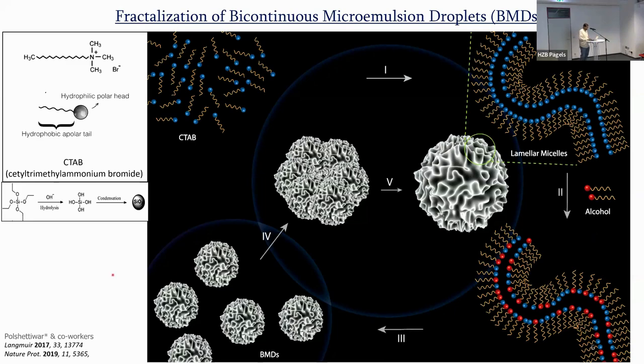Now, if you look at the way we synthesize the silica, right? This is a simple organic reaction. You take this tetraethoxysilane molecule, you hydrolyze, you get a silicic acid, and then you condense and polycondense, you get a silica. That's a typical silica synthesis. If I follow this protocol, you will get a bulk silica, right? The sand on the beach. However, what we wanted was to control the size and the morphology, and for that you need some sort of templated synthesis. You need to create an artificial template into which the silica can flow.